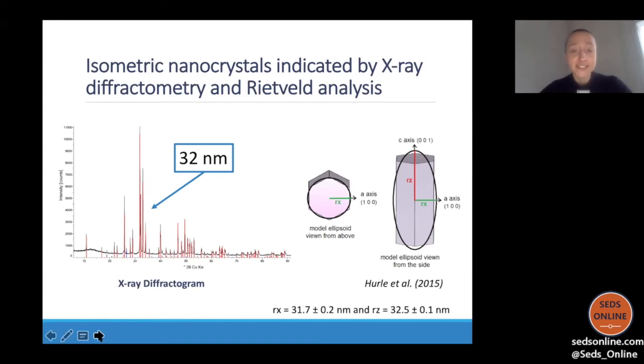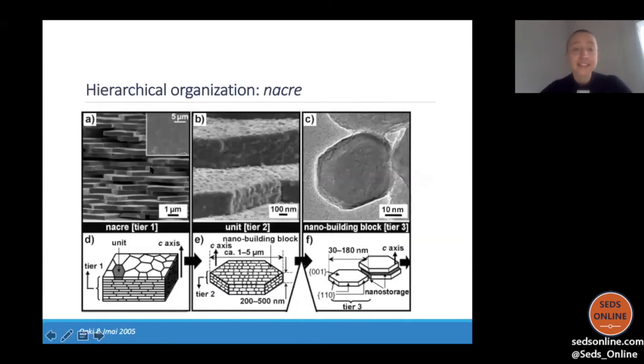So this is not exactly what we have seen on our EBSD map. And this is not unexpected, because in carbonates, which are again our reference group, biominerals are typically organized in a hierarchical way. So nacre, which is the go-to biomineral for all kind of studies in a way, we have these nacre platelets that are, I don't want to say macroscopic, but they're large scattering domains, but they are actually made of nanocrystals, which are glued together with organics. So we think that what we see here is that the X-ray diffraction is showing us the nanocrystals inside the larger grains that we see in EBSD.